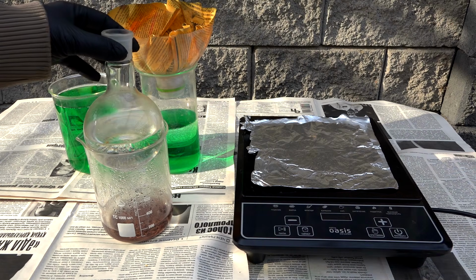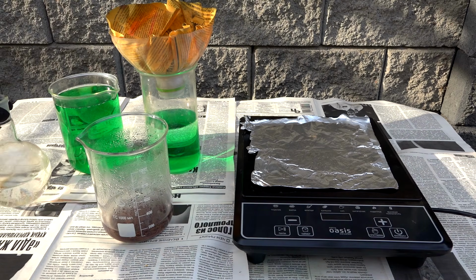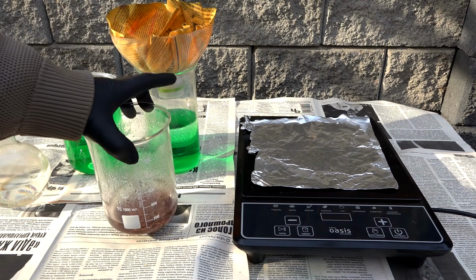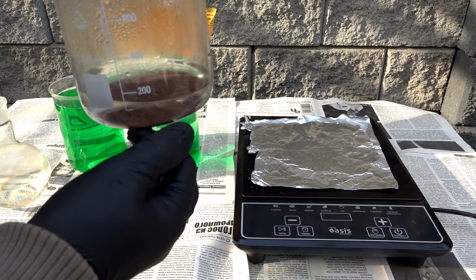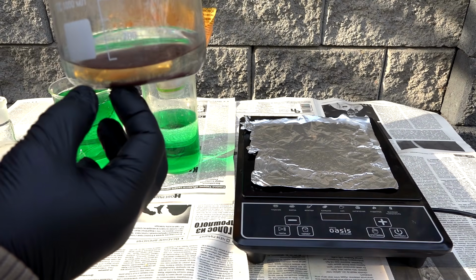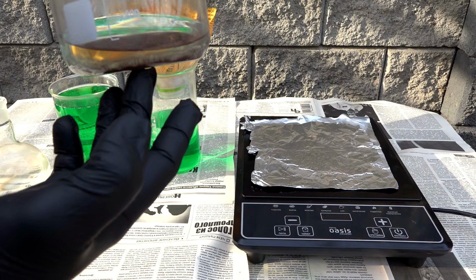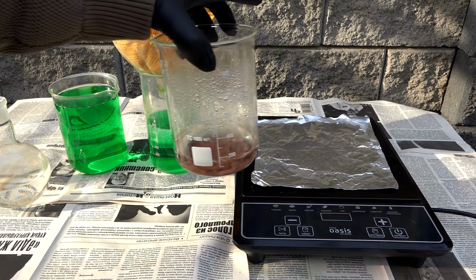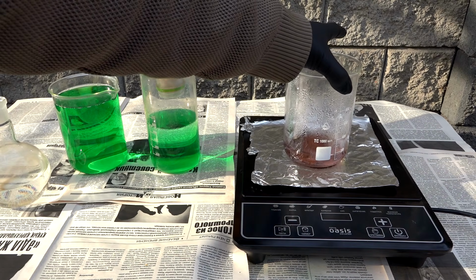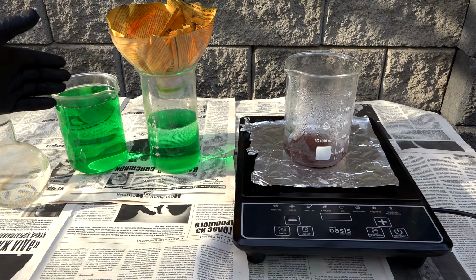Yesterday, I filtered the gold precipitate, poured it all into a beaker, and added a little alcohol to neutralize any remaining nitric acid. Now I want to clean the gold precipitate with sulfuric acid, boiling the precipitate. A slight white cloud formed overnight, most likely lead.